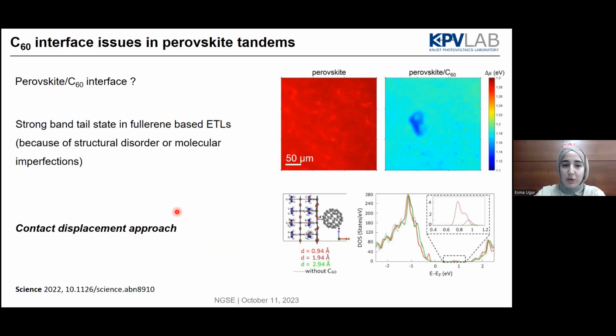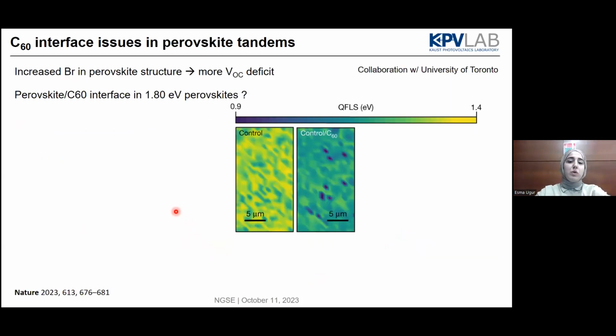So for our PIN devices we are also using this approach, but recently we have also been working on these perovskite C60 interfaces. There was a collaboration with the University of Toronto on wider bandgap. If you have more bromide in the perovskite structure, you have more voltage deficit. This is also what we are seeing in the 1.6 eV, 1.8 eV, 2 eV perovskites. So why is this happening?